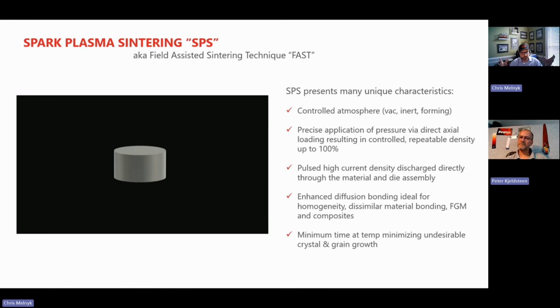So of course, the applied force is a mathematical number there. In standard powder compaction, it's typically 500, 600 megapascal. So it's in the low range compared to cold pressing. But also the tool, absolutely. If it's a graphite tool, it's difficult to press that hard. Exactly, and tooling failure would inevitably happen there. The difference here is, typically in cold pressing, you're using tool steels. They're very strong. You're basically just trying to keep something in a green form. So it's just a different animal.